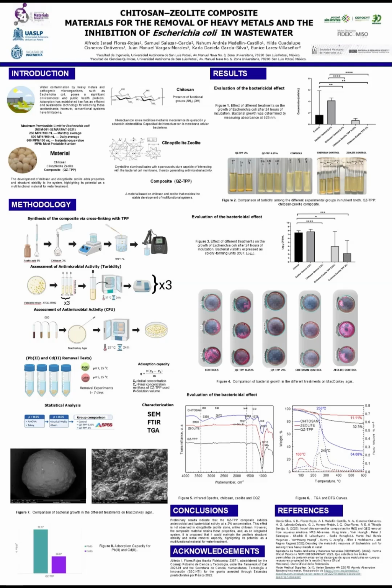The lead and cadmium removal tests were conducted using solutions containing 200 milligrams per liter of each contaminant. 40 milliliters of solution were placed in 50 milliliter polypropylene tubes, and 0.1 grams of composite were added. The samples were kept in contact for 7 days at 25 degrees Celsius, with the pH adjusted, lead to 5, cadmium to 7, using 0.1 N sodium hydroxide and hydrochloric acid solutions.